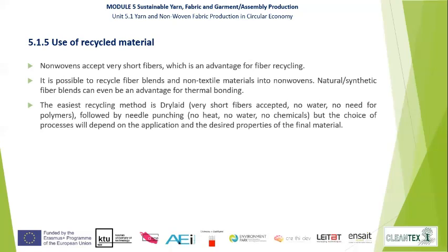The easiest recycling method would be Drylaid followed by needle punching, because very short fibers are accepted in Drylaid process with no water, no need for polymers, no need to heat, and no chemicals in the needle punching process. But the choice of process will depend on the application and the desired properties of the final material.